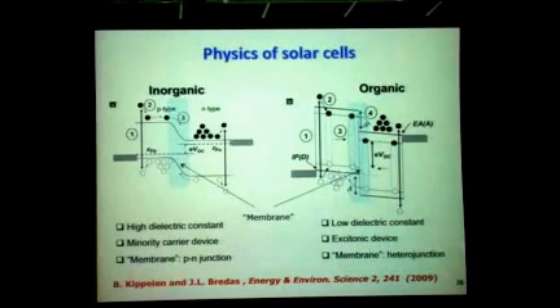In organic materials, this goes back to the HOMO and LUMO levels which I drew earlier in some of these diagrams. The membrane here is obtained by forming heterojunctions between dissimilar materials, one usually having donor-like properties, another having acceptor-like properties. Again, you're generating excitons, which are bound electron-hole pairs. They have larger binding energy than excitons in inorganic materials, so you have to break those up. But when they break up, you can inject electrons into the electron transport layer and holes into the hole transport layer.